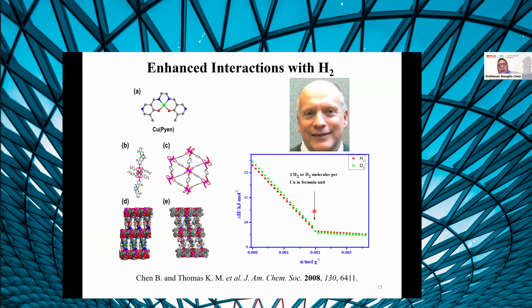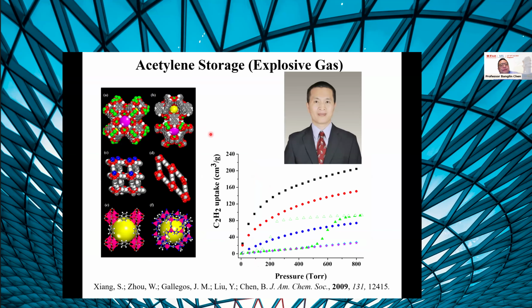Furthermore, these materials show kinetic separation for hydrogen and deuterium, but it is still very challenging to further enhance the interaction of MOF material with hydrogen. And recently, the group from Jeff Long made some progress to have even higher hydrogen interaction. And so the open metal site apparently will be useful for other gas storage. For example, we realize a high density of open metal sites will have stronger interaction with acetylene, and then the acetylene uptake will be very high, because acetylene storage needs to be realized at low pressure and room temperature because of its explosive nature.